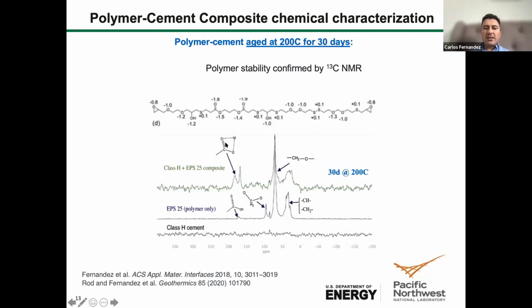For example, in this case, this ester breaks and forms a carboxylate that can interact with the calcium of the cement and form a coordination bond. So there will be changes in the peaks, but that doesn't mean that the polymer is unstable. It's just the polymer interacting with the cement matrix, and that's what we want. So 30 days, 200 Celsius, the polymer is still intact and interacting with cement, and this is for cement H.